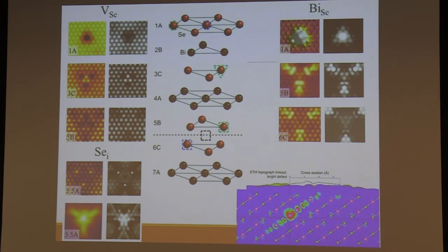In fact, it's interesting because this study kind of contradicted our formation energy plots, in that they found many more vacancies in this third layer. But when we calculated the energetics, we always found that the vacancies on the top or down here are lower in energy.